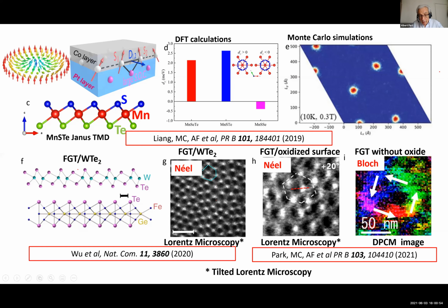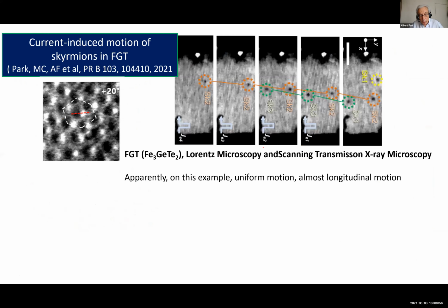So this result is interesting, and even more interesting if one looks at what can be done for the current-induced motion of skyrmions. So in a track of FGT, with a current pulse, one sees that this skyrmion, for example, moves upward from this position after one pulse to this position, to this position. And this is another, for the green one. And the interesting result is that relatively good velocity can be obtained as in 3D materials, but also